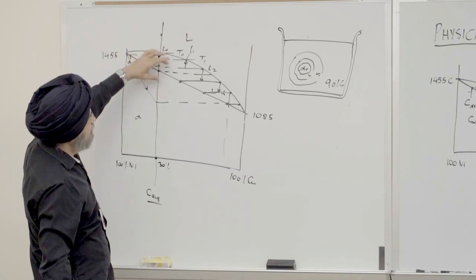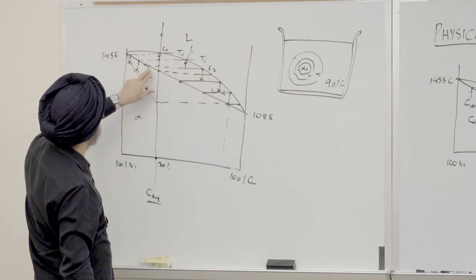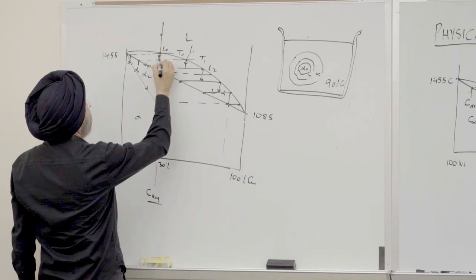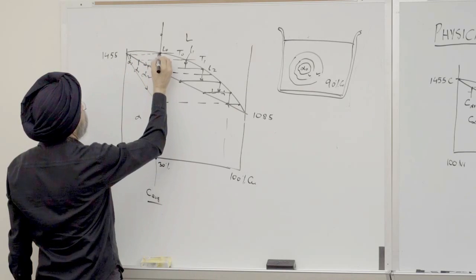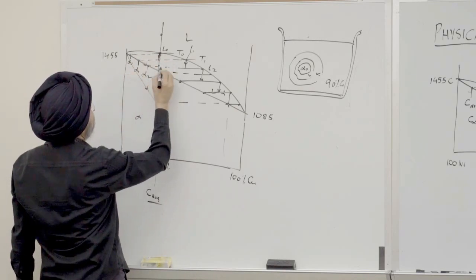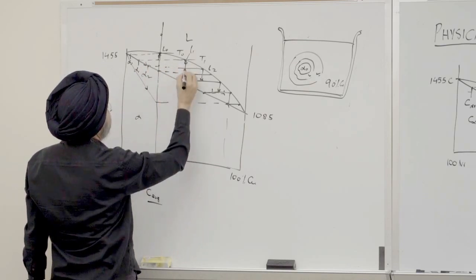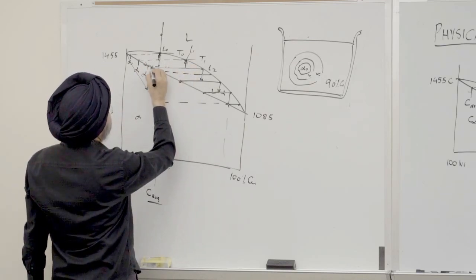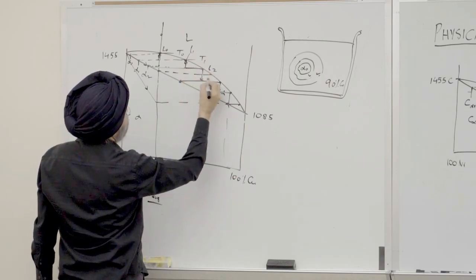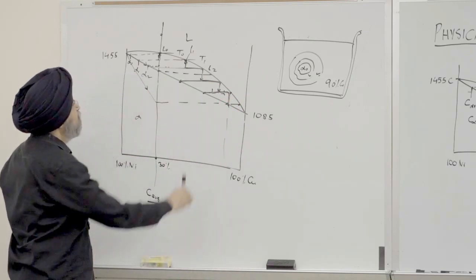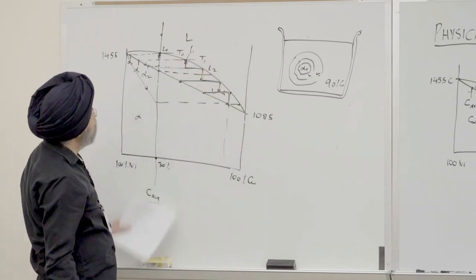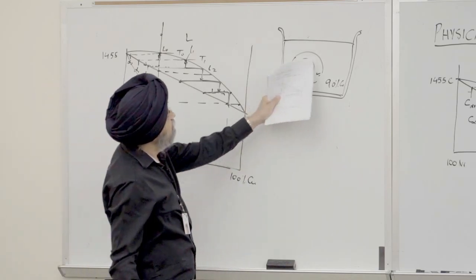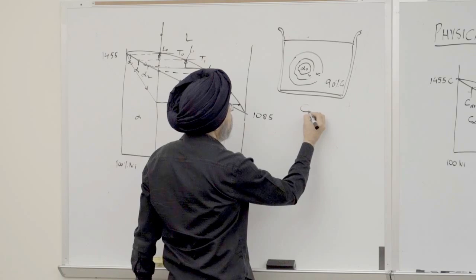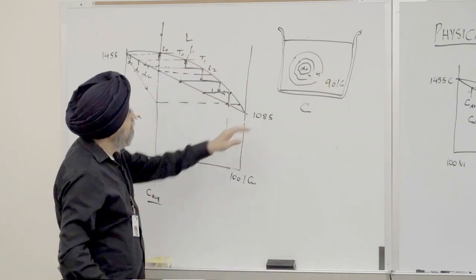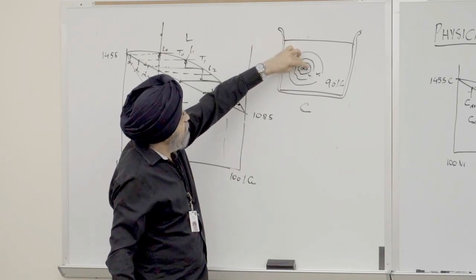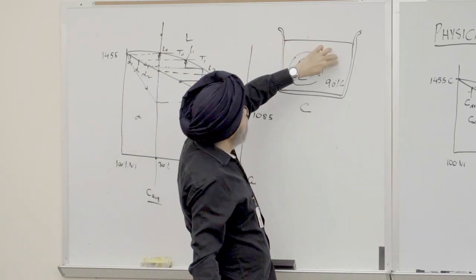because we are freezing at a very fast rate. The way we're freezing is, it is true that at this point, this is the composition of solid, but then we jump over here, that's the composition of the solid, that's the composition of liquid. But now, this is the composition of liquid, that's the composition of solid, and so we have this staircase thing going down. So the liquid composition that is freezing keeps on increasing. So now you can see that if you take the average, it'll come to C. So now you have this alloy which is highly segregated. You have very low copper content over here, very high copper content over here.